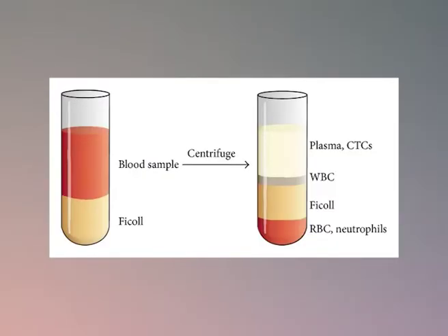In other words, the gradient is such that the density at any level is less than the density of any level lower in the tube, but greater than that of any level higher in the tube. The standard gradient tube is made up of layers of two liquids mixed in varying proportions so that each layer has a different density. When completed, a density gradient tube usually has 6 to 8 layers. In this experiment, one can not only compare the glass particles but also calibrate the density column.